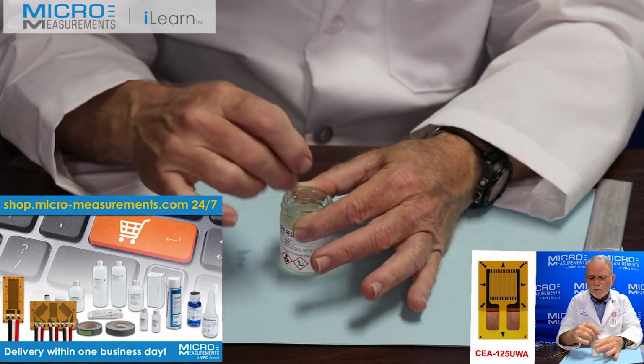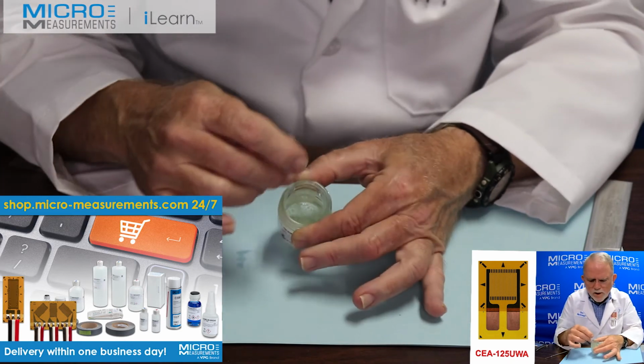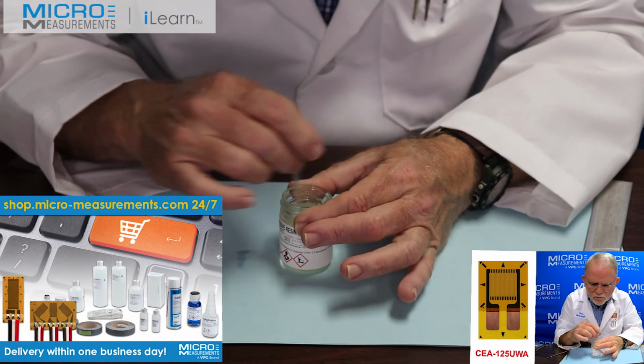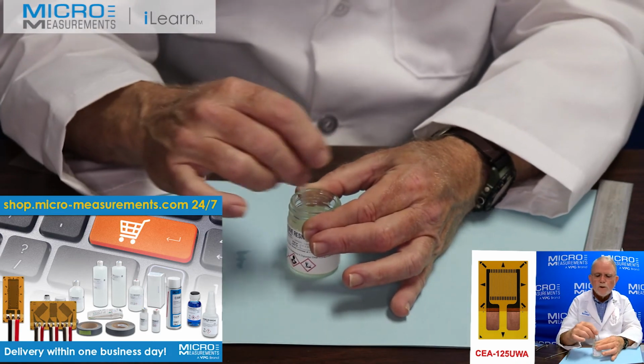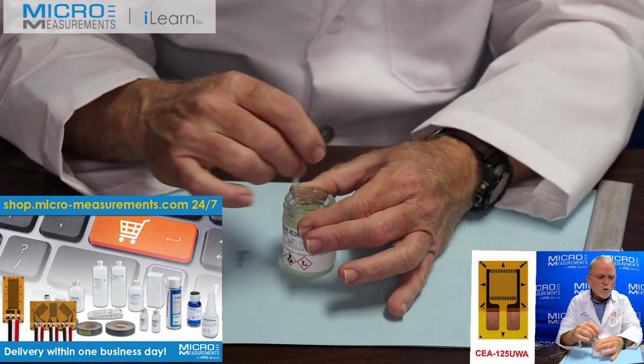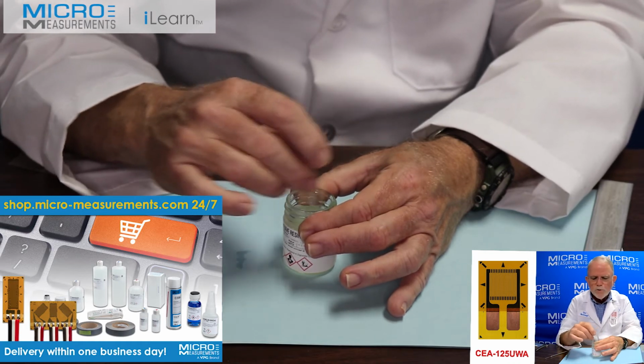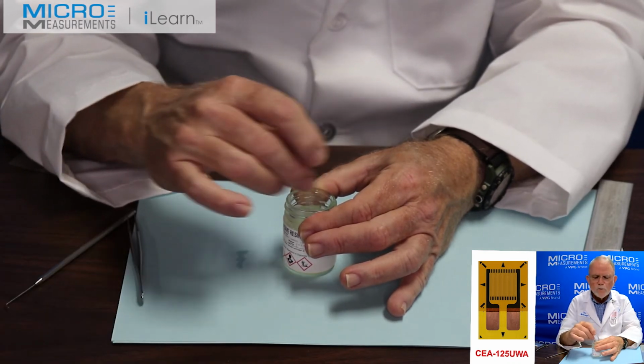Now, as you're mixing this material, you might notice, oh my goodness, look, there's all kinds of bubbles down in there. Is this going to be a problem? It really shouldn't be, because we're going to clamp it up, and when we smear the adhesive out, we'll get rid of all of those little bubbles.